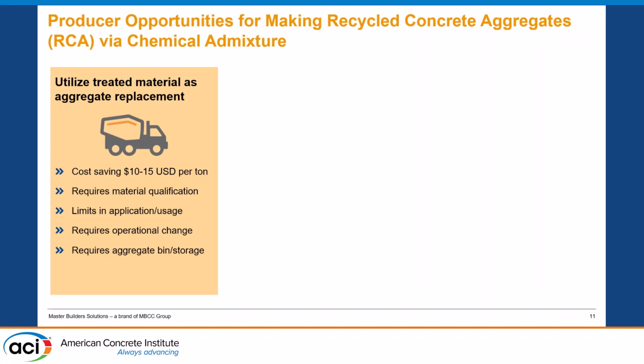However, it requires material qualification, so you need to know how the aggregates that you just generated look like. There are some limits in application and usage where you're going to use that concrete. You have to do the durability testing, you have to do the mechanical properties testing to ensure that the concrete will be usable. It requires some level of operational change. You will have to treat the returned concrete and generate it. You will have to move the aggregates that you generated into a stockpile, and you will be able to choose when to use and when not to use that aggregate according to the applications that you're selling the concrete to.